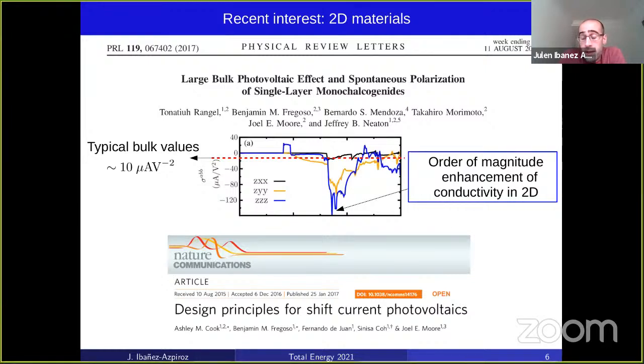Another line of recent research that has been pushed forward is that of two-dimensional materials. Again, the upper work is a density functional theory work where very large shift current photoconductivities were predicted in single layer monochalcogenides. So here we see that the photoconductivity reaches up to 100 microampere per volt squared, whereas the typical bulk values are of order 10. So there is an order of magnitude enhancement when the dimensionality is reduced to 2 dimensions. And this was mainly ascribed to the strong Van Hove singularities of the density of states in 2D.